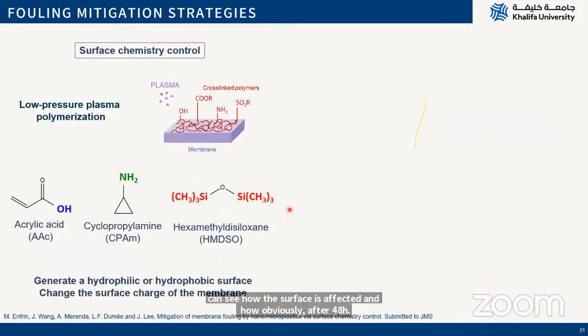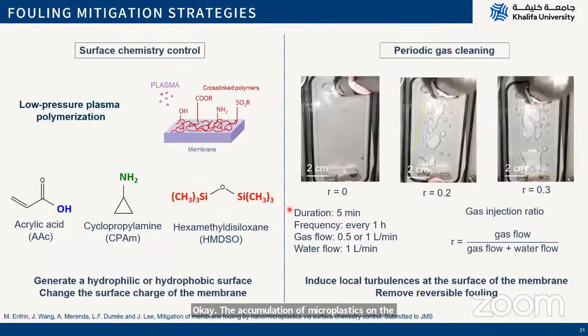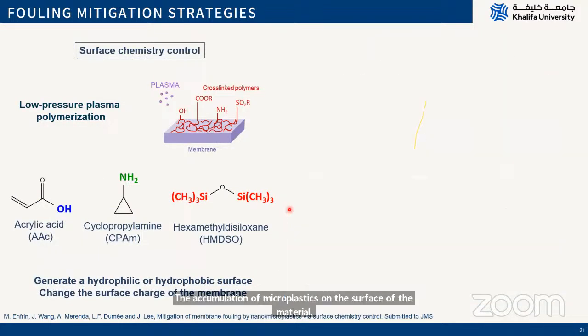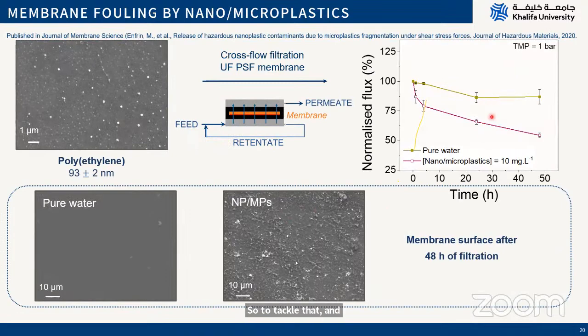But I want to highlight two things. Here, for instance, you can see the surface of a UF membrane, ultrafiltration, after filtration with pure water. A couple of dust things here, but quite pure, the surface is quite nice. After filtration with microplastics in the solution, you can see how the surface is affected, and how obviously after 48 hours there is accumulation of microplastics on the surface of the material. And this led obviously to some decay in flux, very strong changes from the fouling occurring.